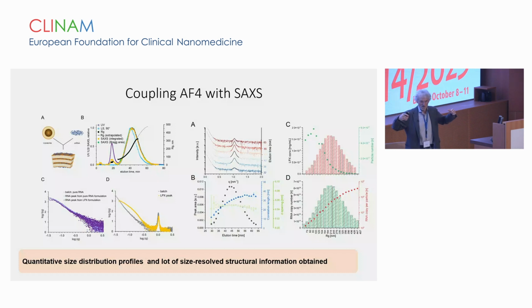We also like to expand it to parameters which we call fractal dimension, because we could correlate that with activity, so you get lots of quantitative information. I think this is something which has the potential to be regularly applied for many, many different nanoparticle systems, liposomes, lipid nanoparticles, polymer particles, and so on, because it's quantitative as it is, and it can be then correlated to lab methods.